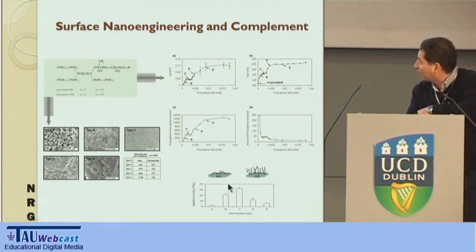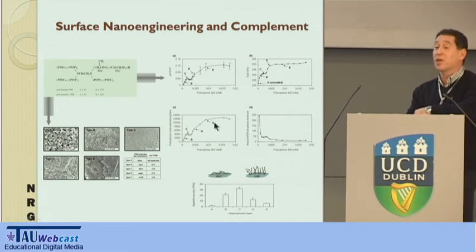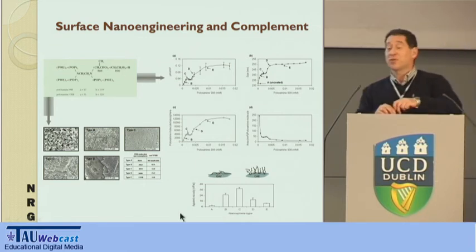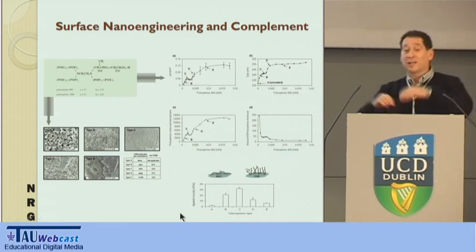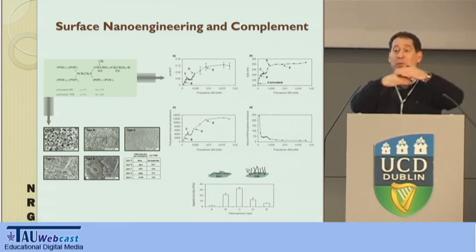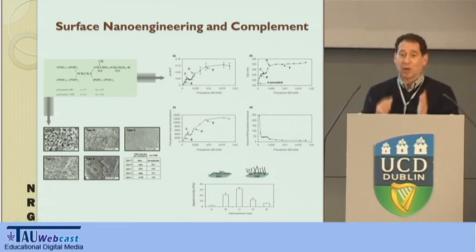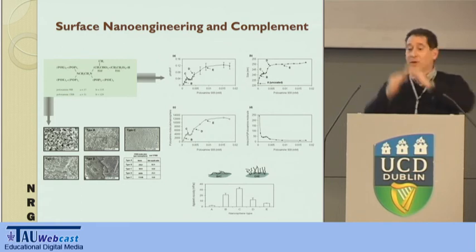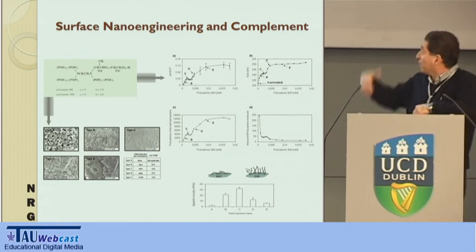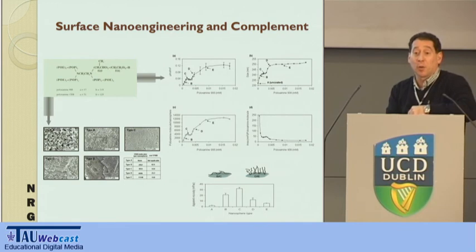And that was an interpretation of the polymer conformational change, especially the ethylene oxide. So you have a brush conformation right at the top, while at the early stage you have a flat conformation. Because of the crowding and water repulsion, the chain starts to expand from the surface. We have actually proven the same thing by atomic force microscopy.